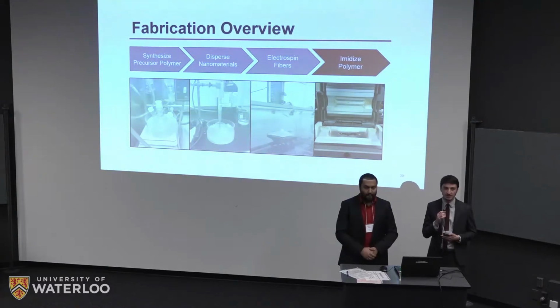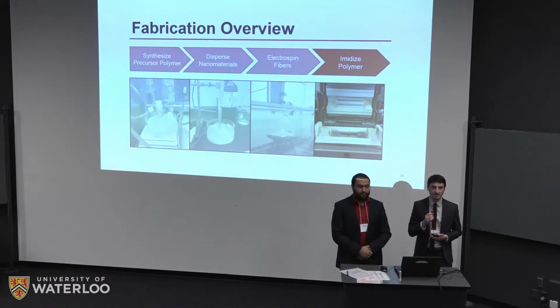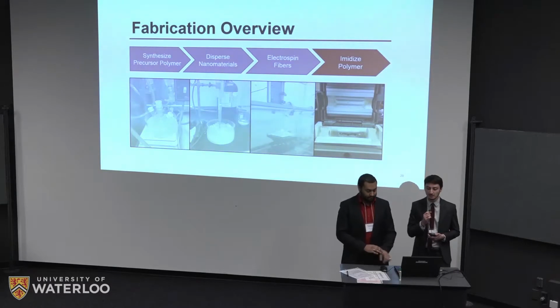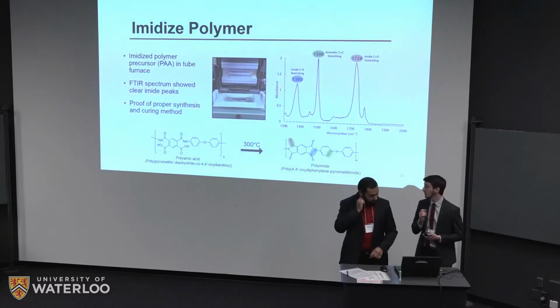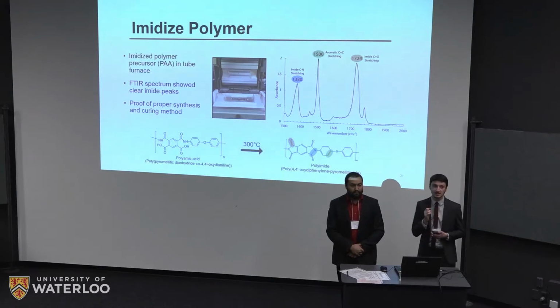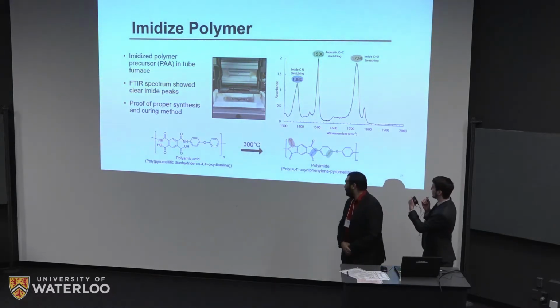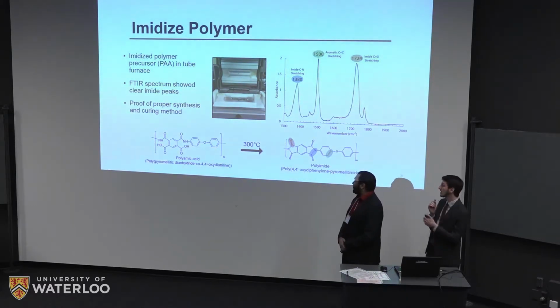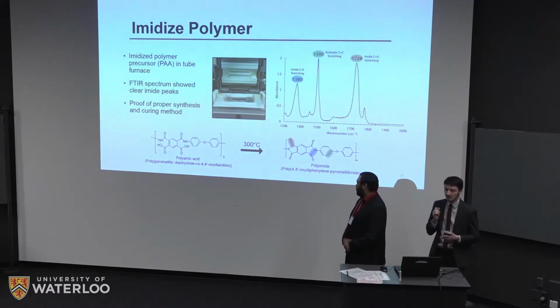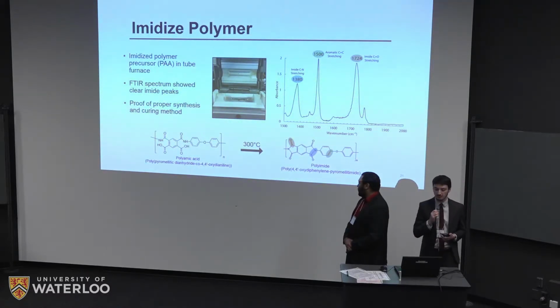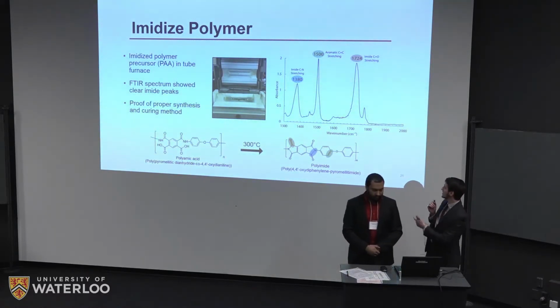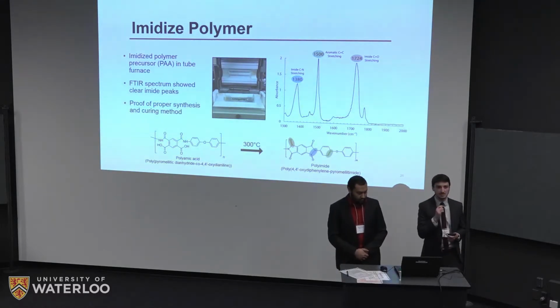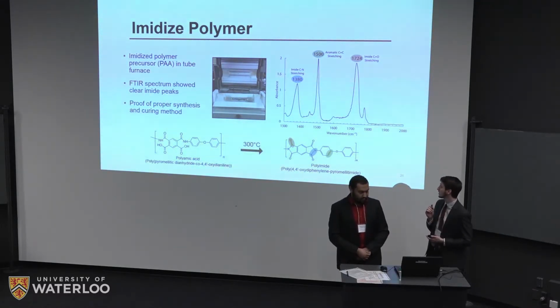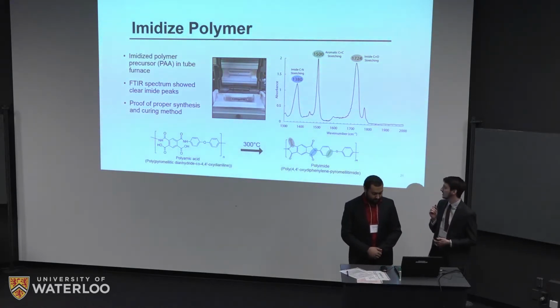After electrospinning our precursor nanocomposite, we then proceeded to our final step, which is imidizing the polymer. This is a temperature treatment where we raise the nanocomposite to 300 degrees Celsius in a tube furnace. This closes the ring that forms the polyimide here, so it converts our polyamic acid into polyimide. This sort of linkage is very important for the thermal properties. As you can see here, especially from the existence of a peak at 1380 wave number, we showed that the imide bond was formed from the C-N stretching that is characteristic of imide.